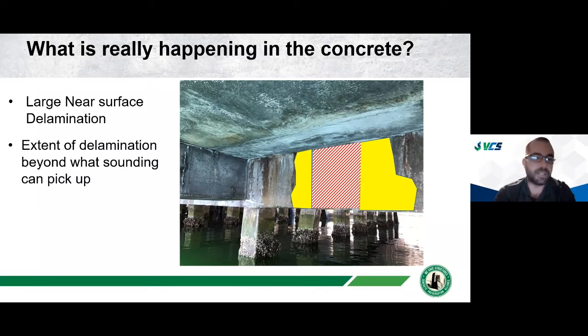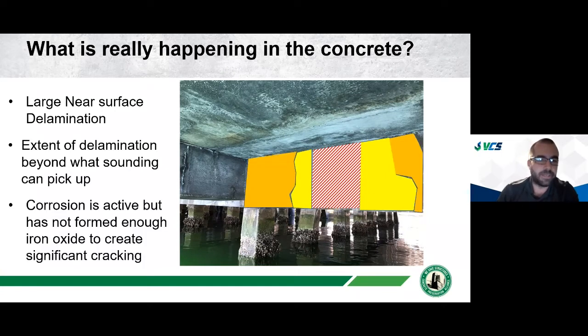Now that's what's physically damaged today. If we go out and repair what's physically damaged today, are we really extending the service life of this structure maybe 20, 50, 40 years, per the client's needs? There are other things happening here. Looking at the condition of this element, we would presume that there are probably areas of active corrosion that haven't created physical damage yet. So the rebar in some of these areas may be starting to corrode, but it hasn't created enough iron oxide to cause delamination. So, where are those areas? And maybe that's the area that I've highlighted here in the orange.